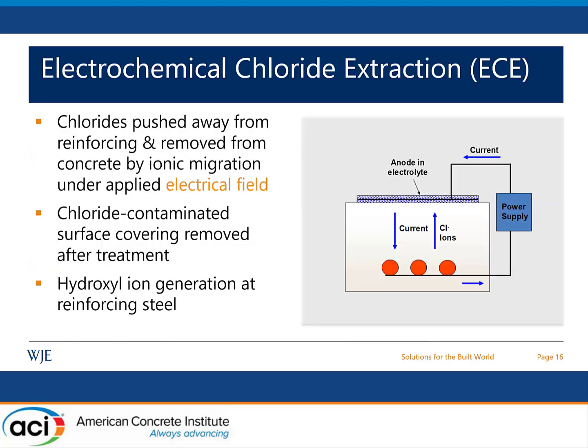So ECE treatment is a surface treatment that's applied to concrete structures where an electrical field is applied between the reinforcing steel and a temporary surface mounted electrode on the surface of the element. This electrical field pushes the chlorides from the reinforcing steel back out of the concrete and into this temporary surface anode, which is then removed after the treatment, taking all of these chlorides out of the concrete with it. As an additional byproduct of this process, there's also hydroxyl ion generation at the reinforcing steel, which can help to repassivate the steel that has already initiated corrosion.